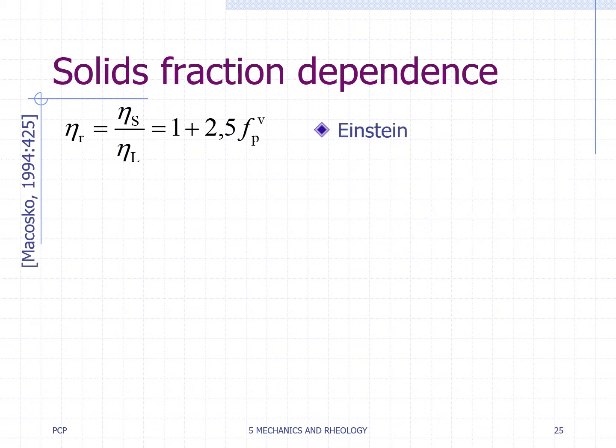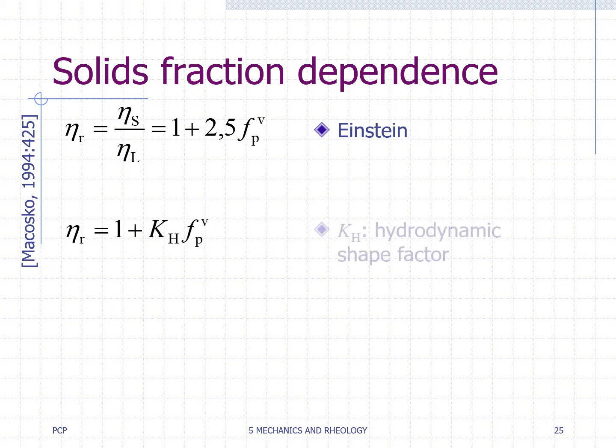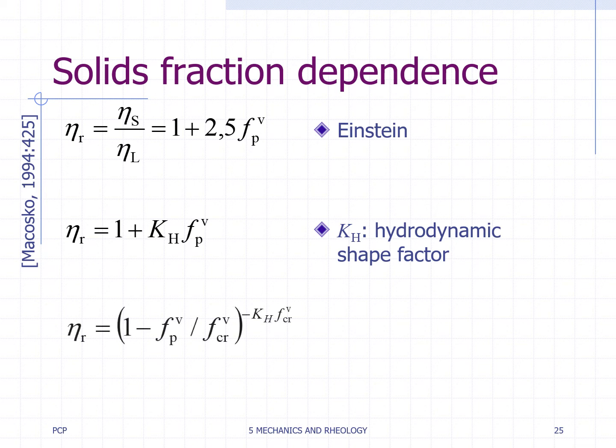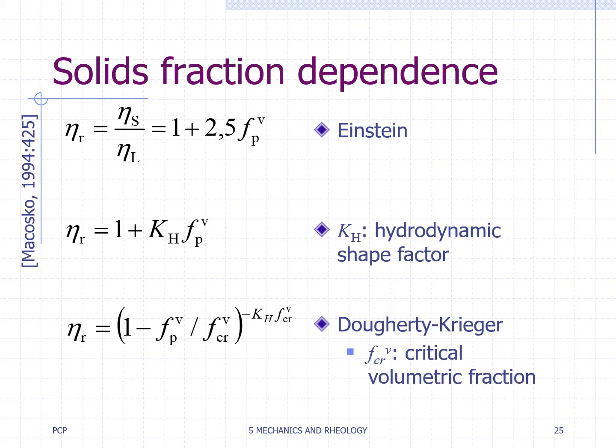A more general equation for the viscosity of a suspension of non-spherical particles introduces Kh as the apparent hydrodynamic shape factor of the particles. In suspensions of particles with an aspect ratio greater than 1, particle rotation during flow produces a larger effective hydrodynamic volume and Kh over 2.5. Rheological data for suspensions of uniform spherical colloidal particles are often approximated by the Dougherty-Krieger equation, where FCR is the critical volume fraction at which flow is blocked.